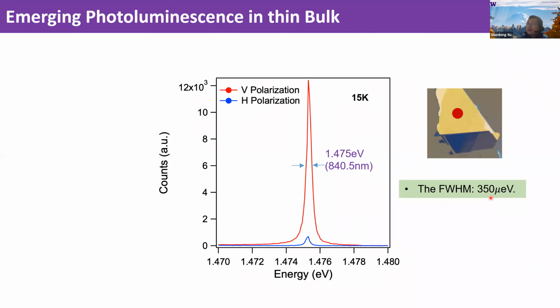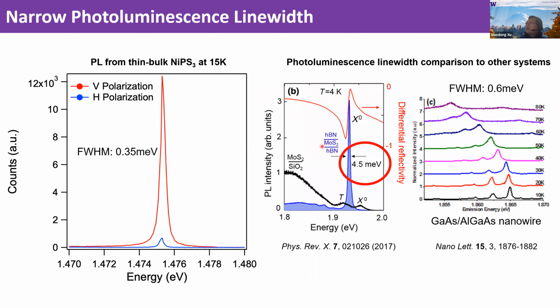So what I mean is narrow. Let's make a comparison. The other type of 2D semiconductor we know, for example TMDs. This is the state of the art of a monolayer MoS2 sandwiched by boron nitride, and as you can see, the linewidth is on the order of 4 meV. So it's about an order of magnitude larger than what we're seeing here in nickel phosphorus trisulfide.